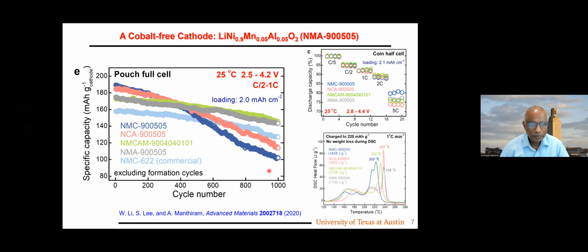cycles. As we see here, the material that does not have any cobalt gives performance similar to or comparable to other cobalt-containing materials. So cobalt may not be necessary as we move forward. The general belief is cobalt may affect the rate capability drastically, but we don't see that. And safety-wise, again, the NMA without any cobalt is right here, which is better than or comparable to other cobalt-containing materials. This was done 2 years back.